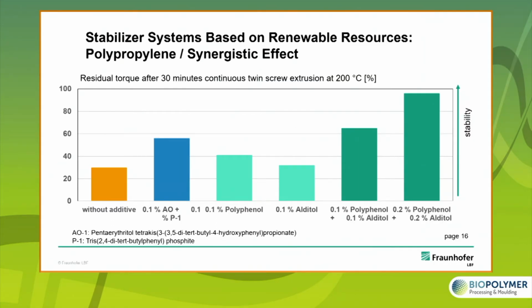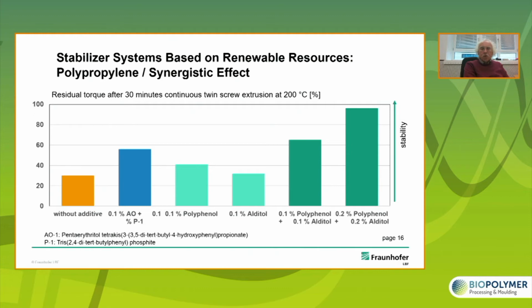So what can these compounds do? Let's first look at this one stabilizer system. We apply a twin screw extrusion at 200 degrees and a polymer, here polypropylene, 30 minutes in circles. That's to say, the load to our plastics is 30 minutes at 200 degrees. We measure the degradation of the material by reducing the residual torque. The lower the residual torque, the higher the damage. The higher the residual torque, the better the stabilization.